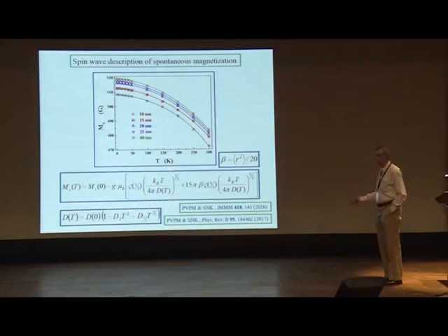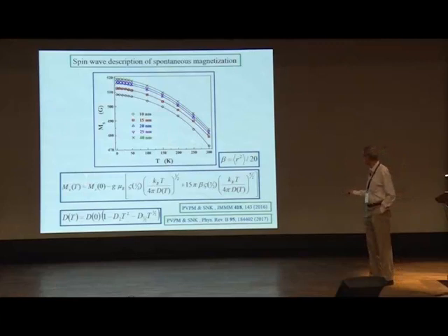It turns out in this case it is the magnon-magnon interaction that renormalizes the spin wave stiffness. So by fitting this, we get the spin wave stiffness constant at absolute zero, and also the thermal renormalization of spin wave stiffness caused mainly by magnon-magnon scattering.